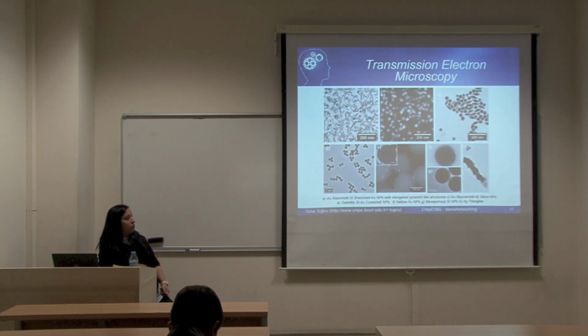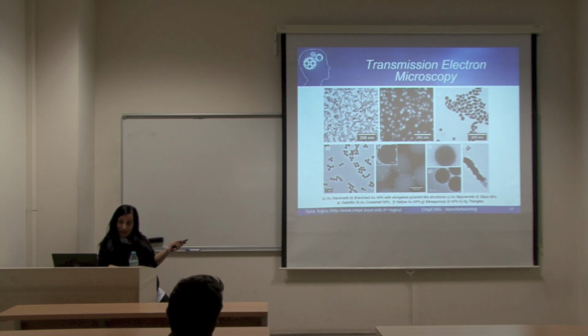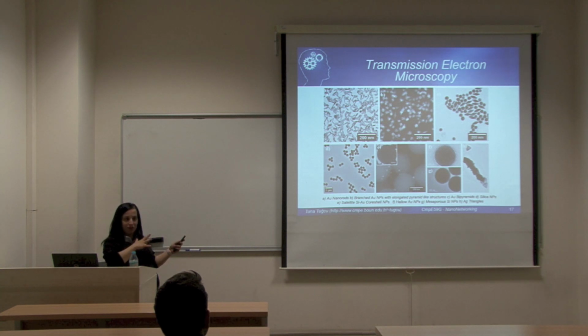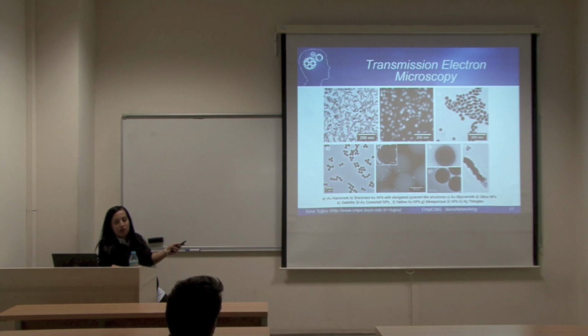Here are some of the images that we have from transmission electron microscopy. These are my images. I wanted to use them to explain how we take them and what they are. Here are gold nanoparticles, gold nanorods, the ones I gave as an example in the beginning. As you see, they're quite homogeneous, but we have some spherical nanoparticles or some short nanorods. Still, this is quite a monodispersed solution. The average size is about 30 nanometers in length and 10 nanometers in diameter.